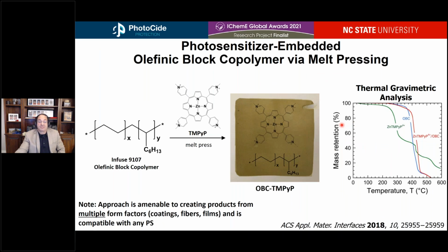We don't have to just use this as a spray coating. We can actually take an olefinic block copolymer like Infuse 9107 and do a solvent cast and melt pressing technique to incorporate our photodynamic agent. And so photodynamic materials, our approach of using these photosensitizers, is amenable to creating products in multiple form factors, whether that's coatings on surfaces, coatings on fibers, incorporated directly into fibers or directly into films, and it's compatible with practically any photosensitizer. And here you can see in the middle panel our olefinic block copolymer that contains our photodynamic agent, which through thermogravimetric analysis shows that we have stability up to 300 degrees Celsius, which is amenable for use in hospital environments.